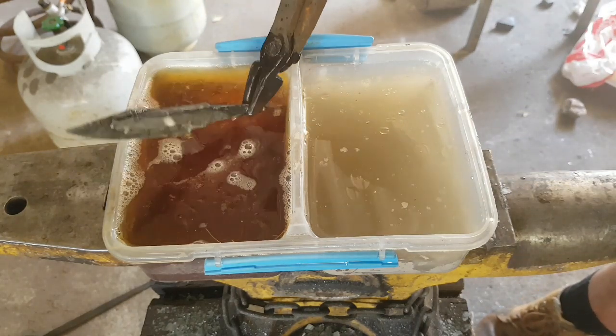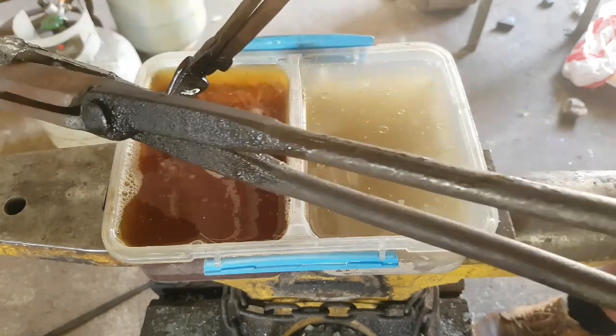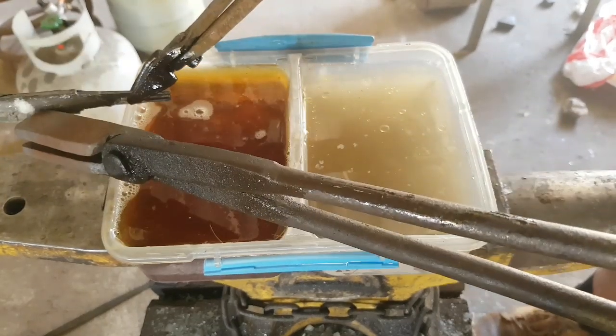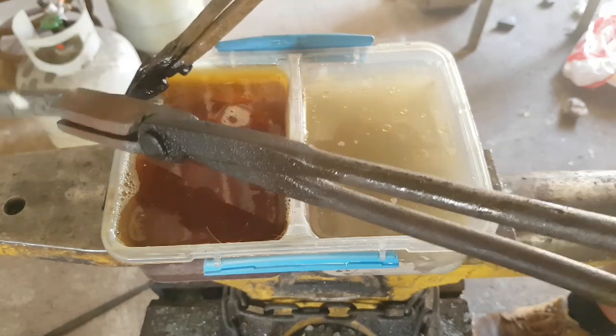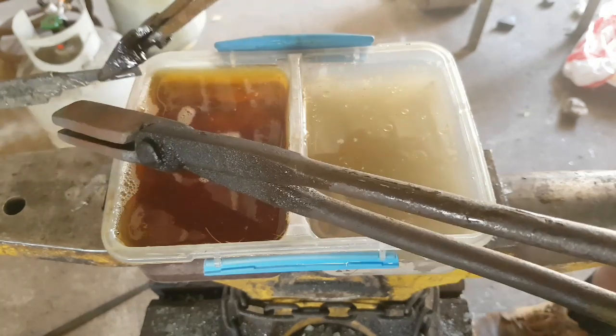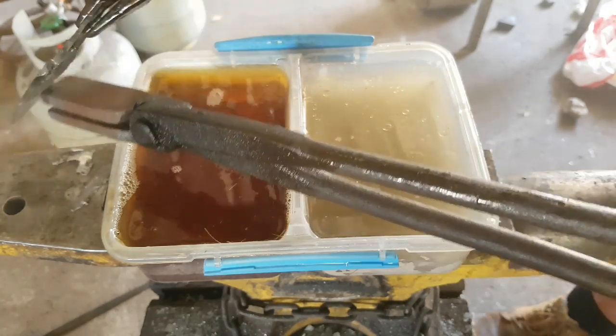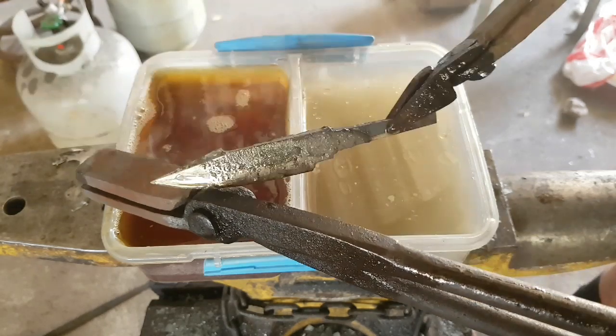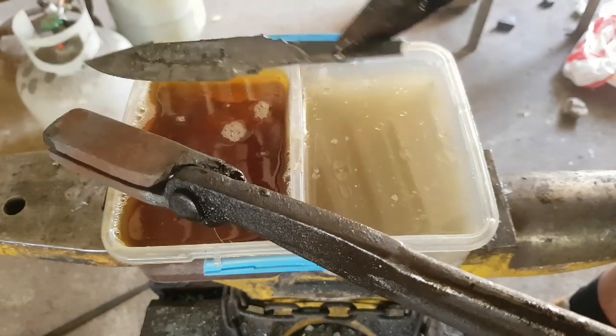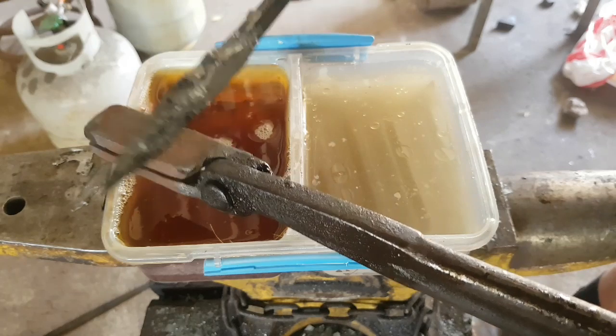If the clay falls off before you quench, then that will prevent a Hamon, but as you'll see, I'll knock off the clay right here with my tongs, and that nice kind of clear line between the edge and the spine where the clay was is a pretty good indicator of Hamon.